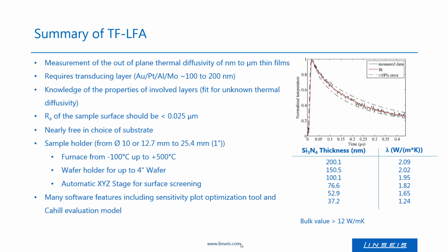So, to sum it up, with the TF-LFA, Linseis developed a powerful tool to characterize thin film samples from the nanometer to micrometer scale, regarding their out-of-plane thermal transport properties. It is a further development of the standard laser flash technique for the measurement of thermal diffusivity. For the determination of the thermal conductivity, the density and the specific heat capacity are needed.